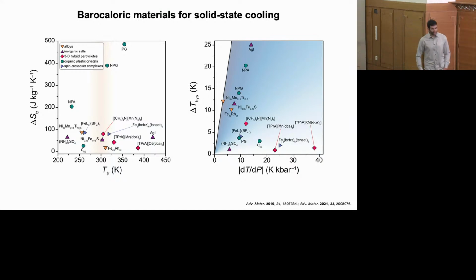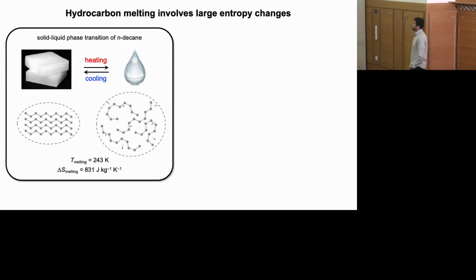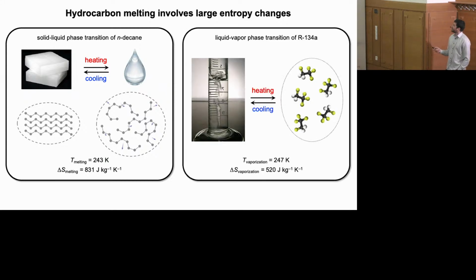And so my research group got interested in this challenge a couple of years ago. In particular, we were inspired by the fact that very simple phase transitions of normal hydrocarbon molecules, things like wax going from a crystalline solid state to a disordered liquid state, feature very high entropy changes. The entropy change for this kind of melting transition is actually higher than the liquid to vapor phase transition of a typical fluorocarbon refrigerant. This comes from the increase in conformational, vibrational and translational degrees of freedom that hydrocarbon molecules have as they transition between these two states.